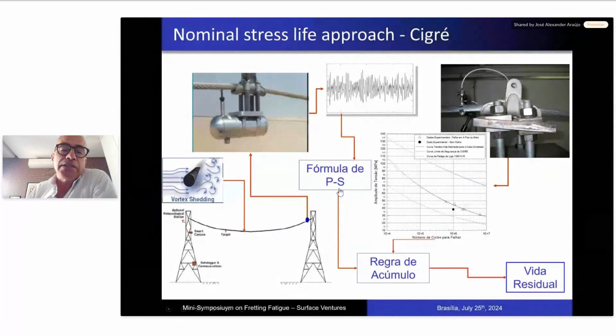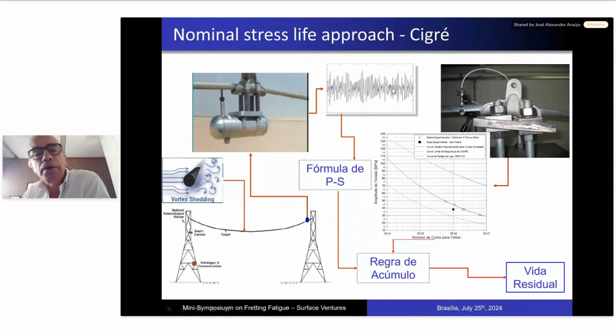We should have in mind that these stresses computed by the Poffenberger-Swart formula, which is applied to this time distribution of displacement, are nominal stresses, okay? And they claim to give the value of the stress at the wire, which is opposite to the last point of contact between the clamp and the conductor. Of course, in reality, it's not these stresses that are breaking the wires, because you have very complicated stresses generated by the contact. It's a much more complicated problem, but this is a nominal stress approach to try to compute a residual life. Okay?